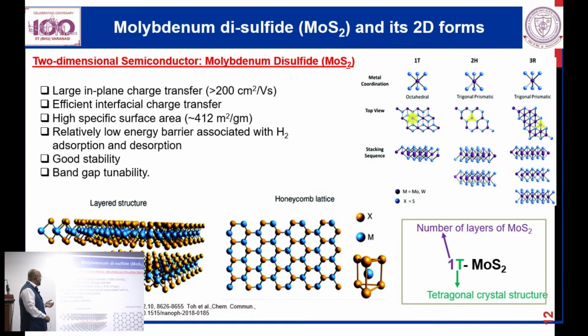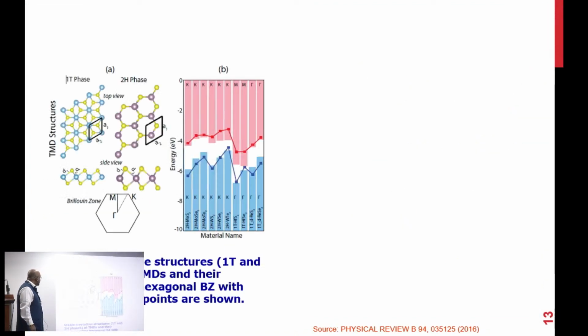So that's the benefit, and then the new formation comes with 2H and 1T. The 2H MoS2 is semiconducting in nature, having a clear band gap, which brings us to our next slide. In this next slide, you see the 1T phase and the 2H phase. They have a clear band gap in 2H, but the moment the phase transforms from 2H to 1T, it transforms from semiconducting to metallic, and that is very important and is utilized for water electrolysis, water catalysis, and that kind of thing.